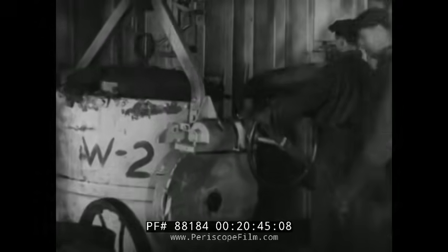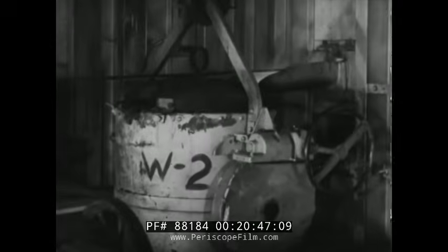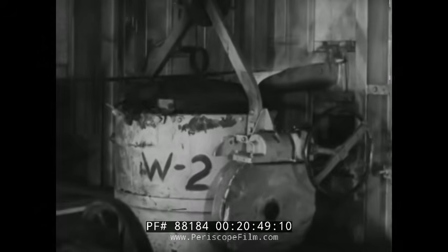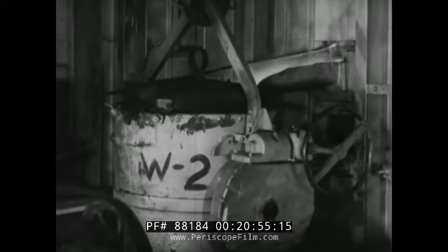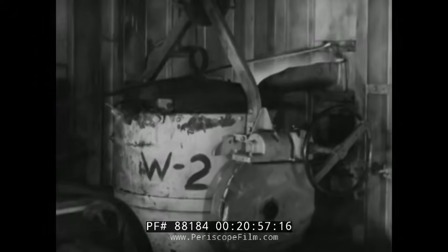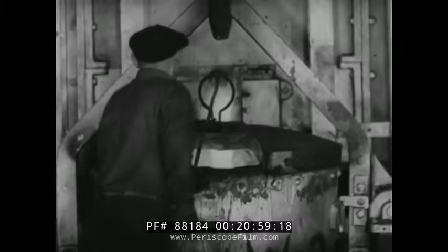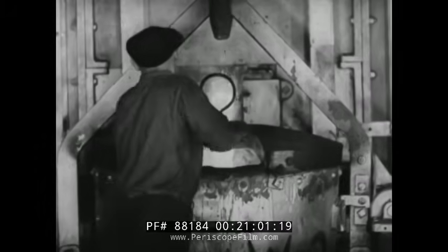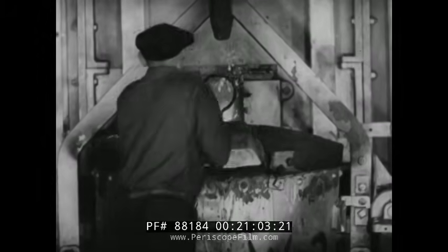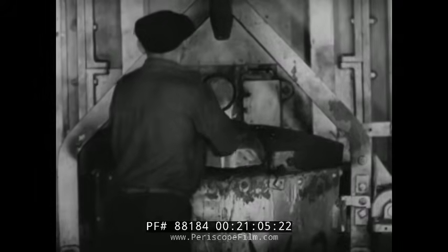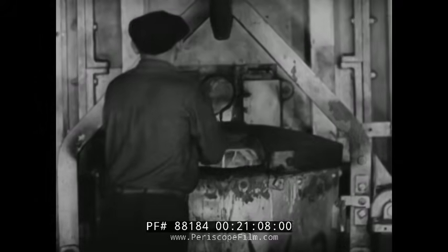A ladle is brought up by the crane and placed under the tapping spout. The tap hole is opened with an iron bar and the white-hot molten metal rushes into the ladle. When the ladle is full, the tap hole is plugged with a ball of moist clay. The ladle is skimmed and taken away to pour.